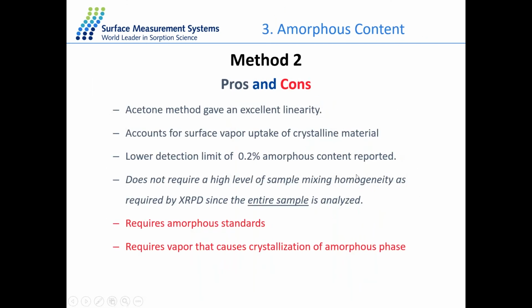So some of the advantages and disadvantages of this method. This method is quite accurate, especially for low amorphous content material compared to some traditional methods. We can get a really reproducible and accurate result with this pre and post crystallization amorphous content method, and we can detect as low as 0.2% amorphous content inside the material. And one of the disadvantages of this method is that we first need to have a standard with no amorphous content as a reference value, and then we also need to find a vapor that will induce the crystallization inside the material.